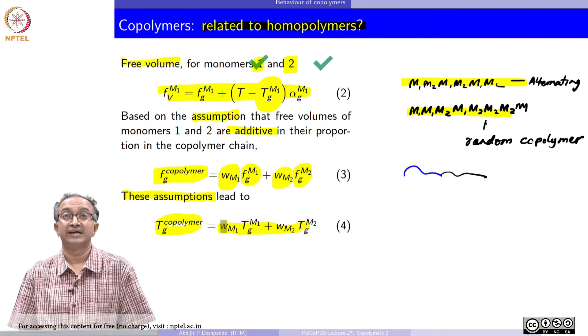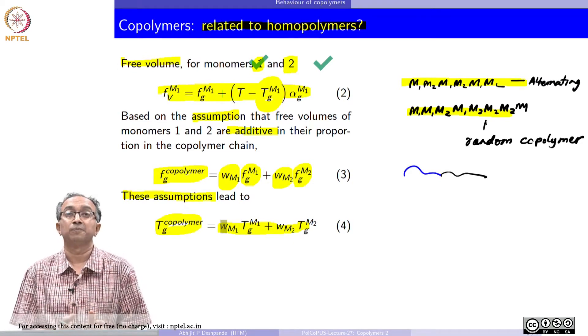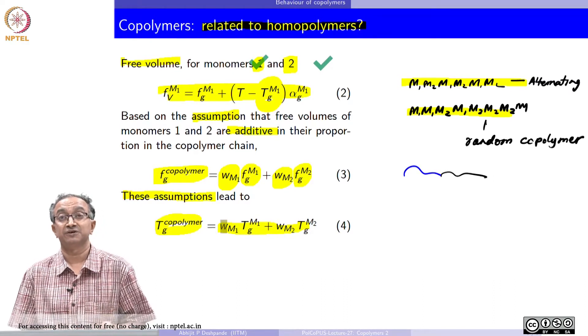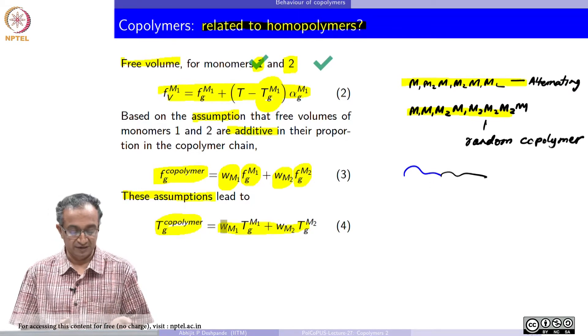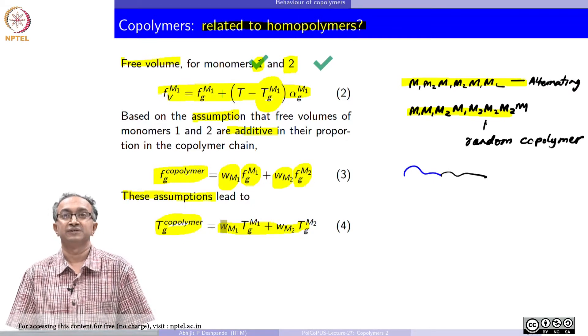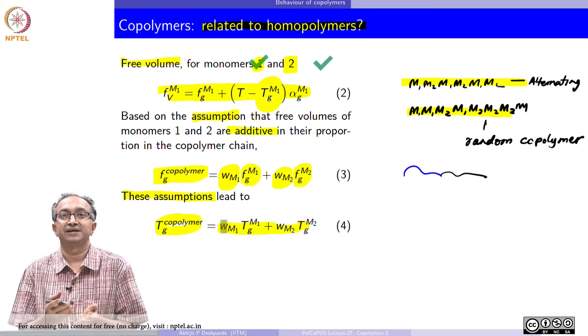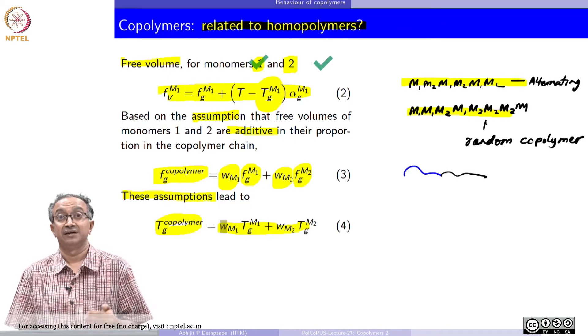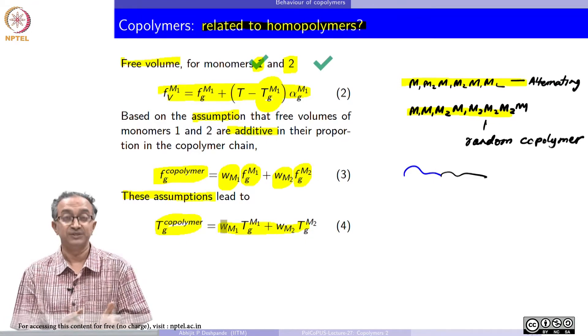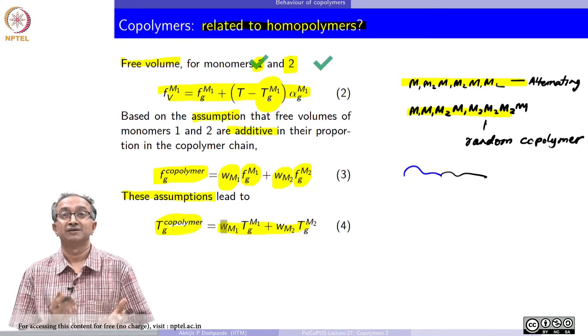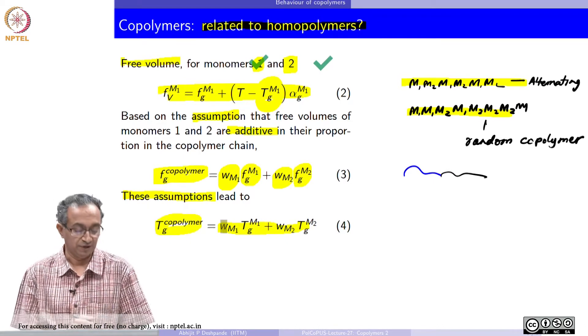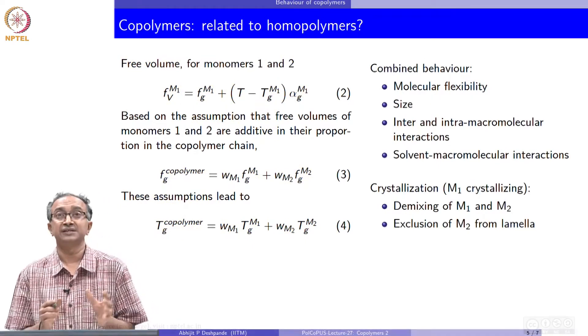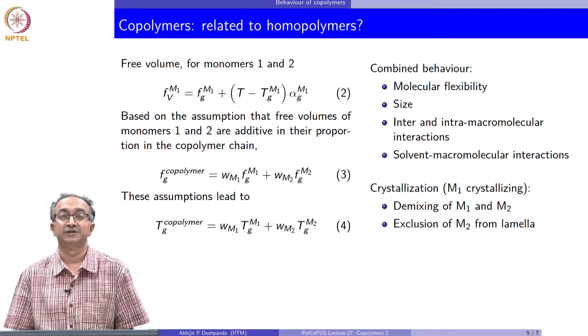Using such a mixing rule we can estimate and understand copolymer properties. This is also useful for targeting: if I have two homopolymers with glass transition temperatures of minus 80 and minus 10 degrees, and my target is a glass transition temperature of minus 40 degrees, such thumb rules tell me what relative ratios to aim for in synthesis. Generally, this combined behavior for alternating and random copolymers can be obtained from knowledge of the homopolymers.